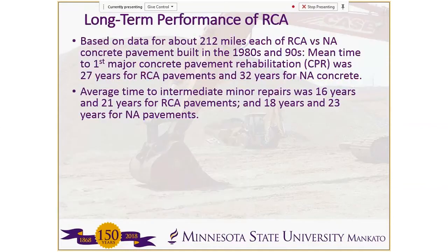So we studied the time it took for the pavements to reach a terminal RQI value of 2.5. And as we expected, in general, the RCA pavements performed a little bit worse than those pavements that were made with the natural aggregates. So based on those comparisons, the mean time to the first major concrete pavement rehabilitation was about 27 years for the RCA pavements and about 32 years for those made with natural aggregates.